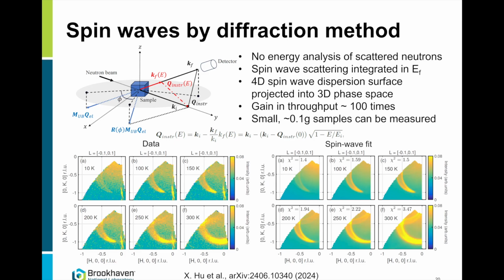So normally in diffraction, only elastic processes are considered. However, all processes are being picked up by the detector. So what we measure, or what we can see in our measurement, is the integration. And so this is the measurement, which shows this nice, interesting signal measured at different temperatures from a 100 milligram sample. Each measurement was like 3 or 4 hours. It is a spin wave spectrum. And here is a simulation of this spin wave spectrum. So what we have discovered is that we can measure a refinable spin wave spectrum, which allows us to determine all 4 Hamiltonian parameters on a very small sample in a very short time.